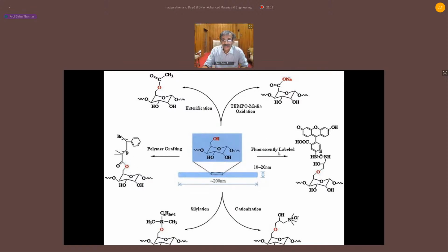You can label fluorescence group on the surface of nanocellulose, and you can do fantastic fluorescence spectroscopy study. And one group in Canada made beautiful sensors. You can do acetylation reaction. This is what we are going to do with Apollo Tyres, acetylation reaction to make them hydrophobic. You can do cationization reaction. So several chemical reactions could be performed on the surface of nanocellulose to overcome the issues of dispersion, to overcome the issues of incompatibility, to overcome the issues of poor interfacial adhesion with non-polar polymers.